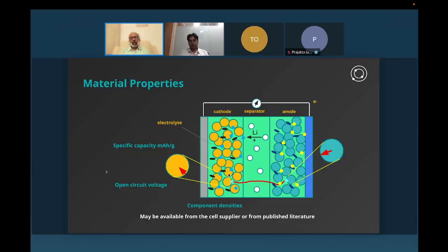So what is needed to describe this for a model? First thing we need are the material properties. And if you look at the cathode side, one is the specific capacity. This is a property of the cathode active material. And another is the open circuit voltage on the cathode side. And then we need the component densities. And we talked about the active material, the binder, and the conductive filler. We need the specific gravity or the density of all these components. So this is on the cathode side.